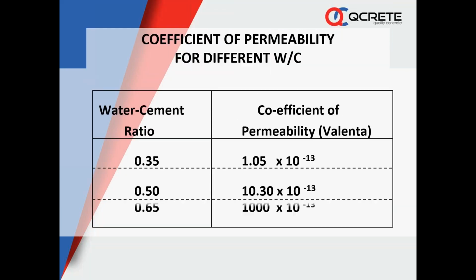So, the importance of water cement ratio: at a water cement ratio of 0.35, your coefficient of permeability is 1.05. As soon as it is increased to 0.5, it increases 10 times. As soon as it increases to 0.65, it increases 1,000 times actually. So while preparing concrete, we have to be very, very careful with our water cement ratio.